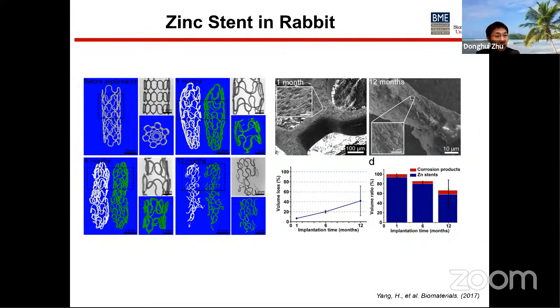These are the micro-CT and SEM imaging showing the volume loss of the material after 6 months, about 20%, and about 40% after 12 months. The corrosion behavior is largely uniform after 1 month; however, some localized corrosion was observed at 12 months.